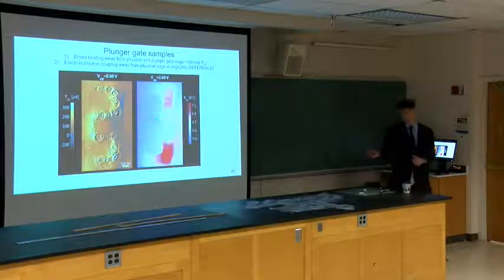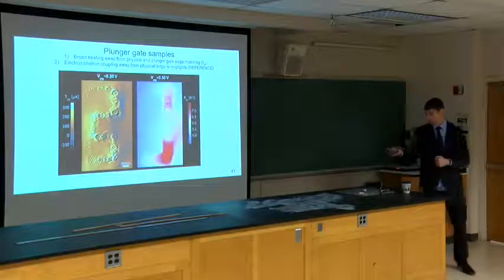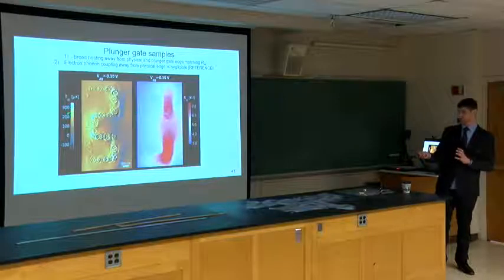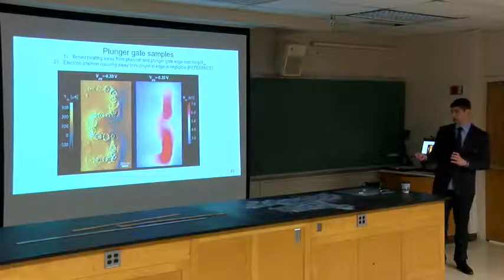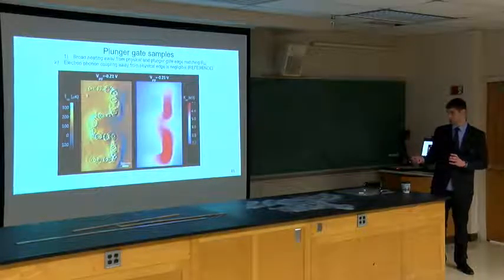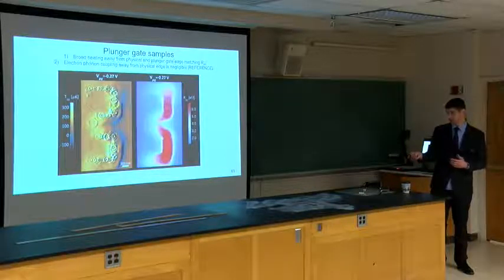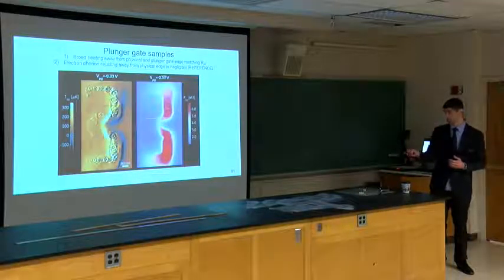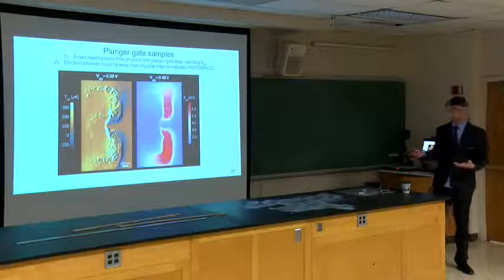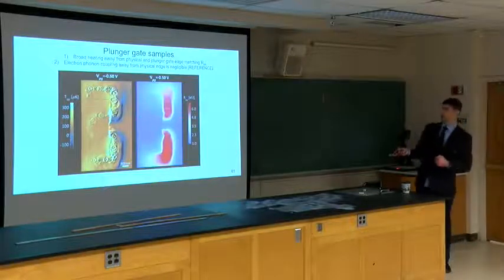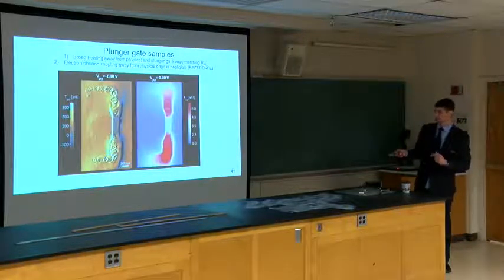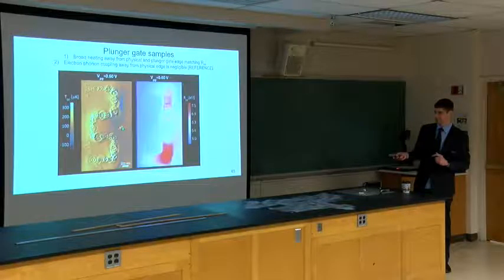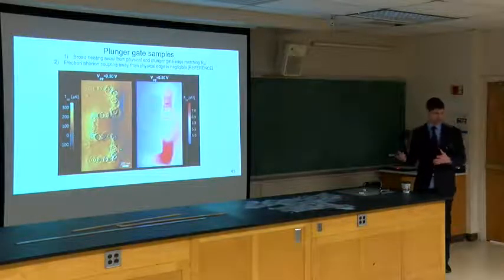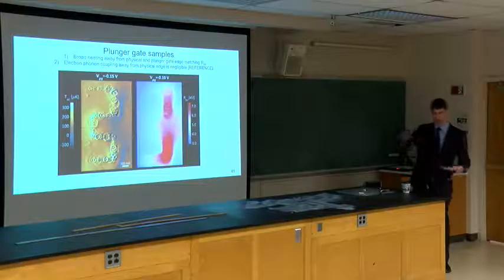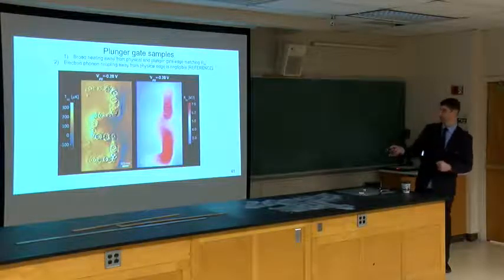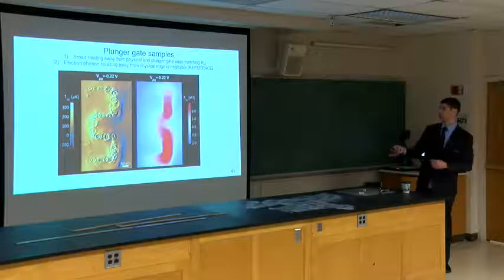So zooming in on one of those plunger gate regions, and all we're doing here is changing the gating in this area. And what we see is first there's the ring structure for changing where we see the phonon scattering, and then we see the resistive change from the scanning gate signal. And they don't match up, except for, well, we see the background, there's a background temperature increase here, but it's not resonance. You can just see it's kind of a broad blob, in a sense, in physics terms.